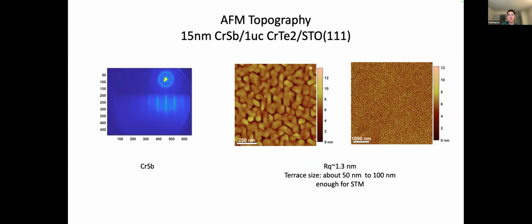And the AFM result of this sample is really good. It shows the chromium antimony terrace with a roughness of about 1.3 nanometer and a terrace size of about 50 to 100 nanometers, which is flat and large enough for STM measurement.